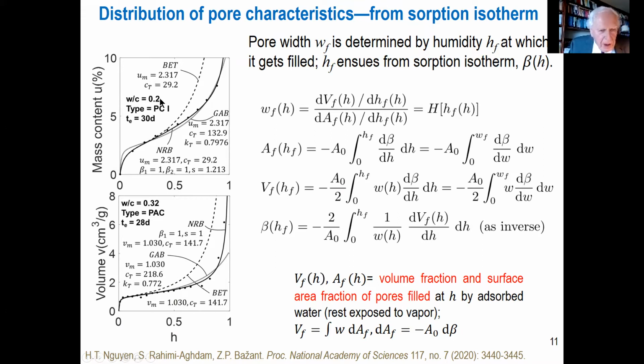It is shown here for a very low water cement ratio, about the limit in modern concretes. It is shown for the classical BET isotherm, dashed, and this is our theoretical prediction. It is also shown for the empirical model GAB, which predicts saturation wrongly but fits reasonably well. But if you change temperature, as I will show later, it has major error. It cannot be used at all, actually.